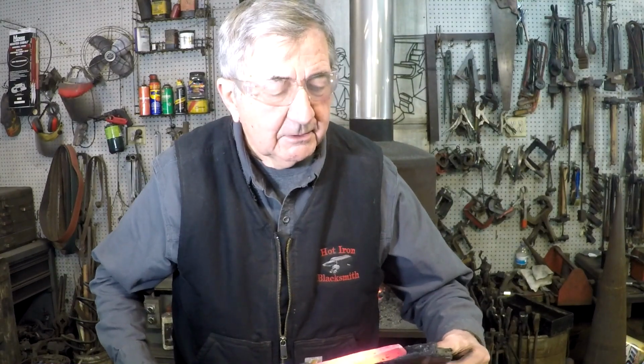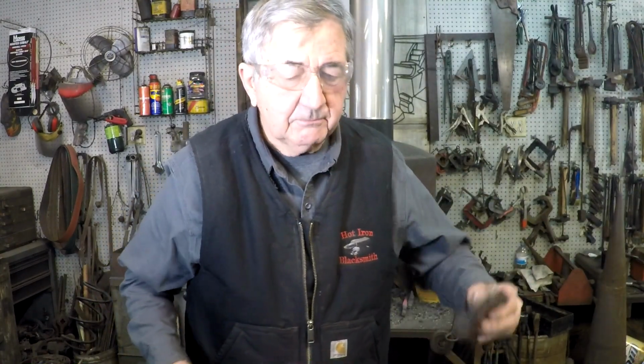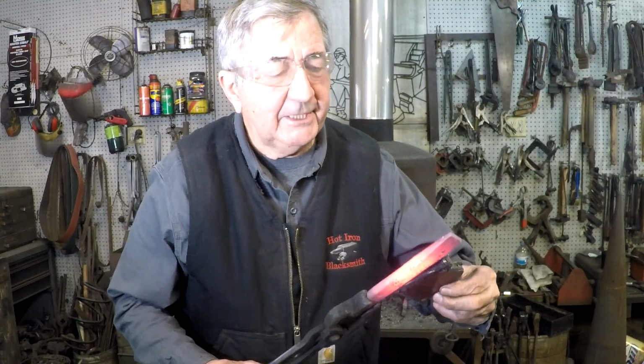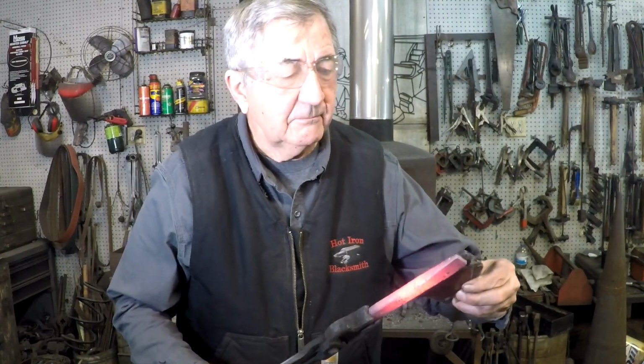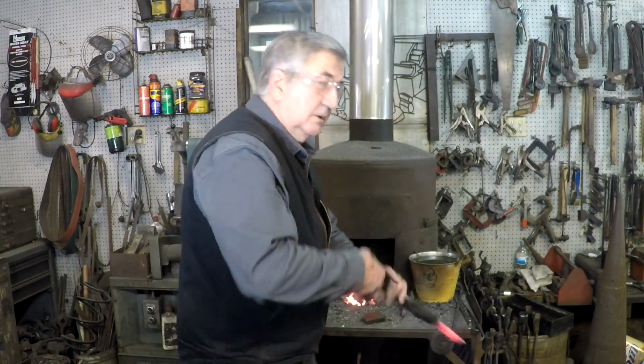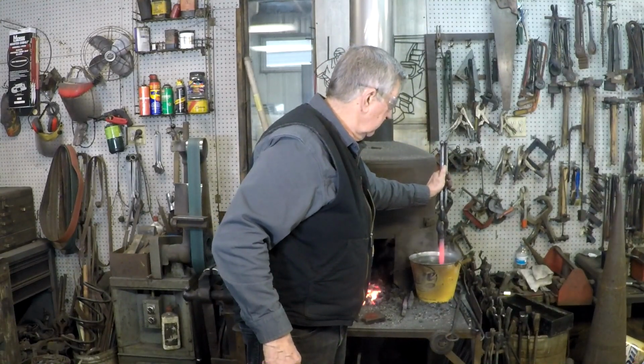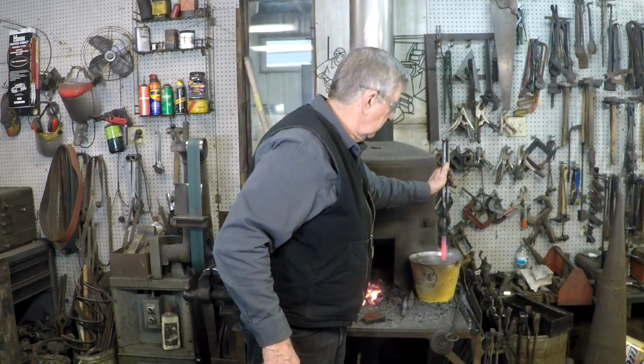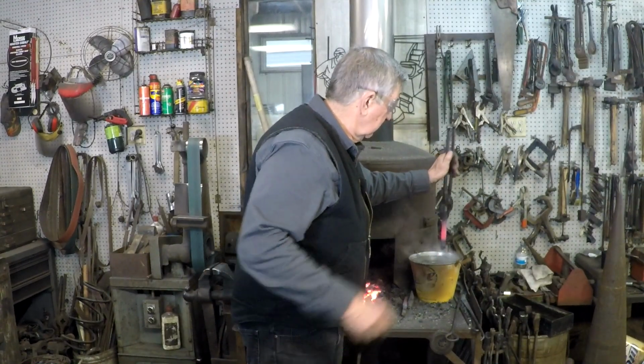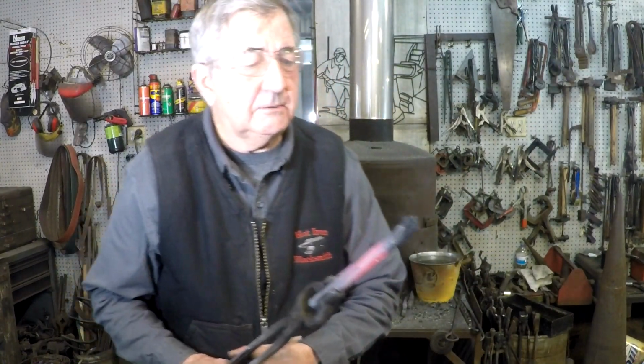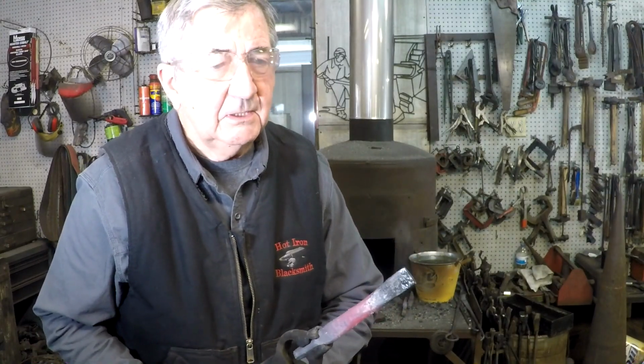This is a slot punch, and it's already been annealed, and we're going to check it to make sure it's up to temperature. It's up to temperature, and that means it's got to be above the magnetic temperature, so it's non-magnetic at this point. And so the next step then is to quench this end. So I have cooled off the end until the very tip of that is wet. I put it in the water about 1.5 inches and cycled up and down in the bucket. It is wet, and that means the end is below the boiling point of water.